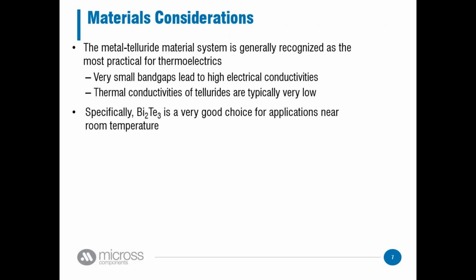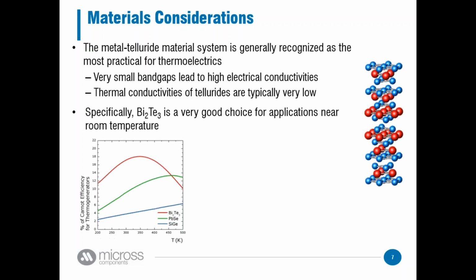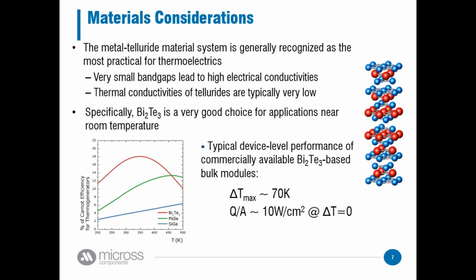Basically because most applications we're concerned with are going to be around room temperature, and bismuth telluride operates the best at room temperature. As you can see, compared to some other materials here, right around 300K, you're going to get the best performance out of bismuth telluride. So if you go and buy a thermoelectric module from Melcor, from Marlow, Custom Thermoelectric or something, it's going to be bismuth telluride, and it's going to be bulk, several millimeter thick elements of N and P type bismuth telluride. The type of performance you're going to get out of a commercial bismuth telluride module like that is a delta T, meaning the maximum temperature difference you will get from a single stage device, of around 70 Kelvin.